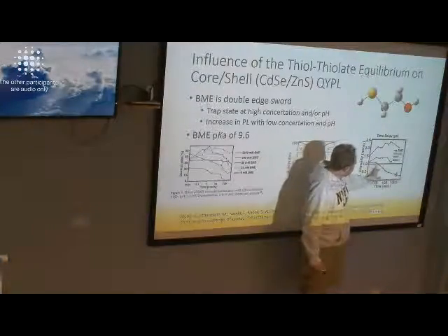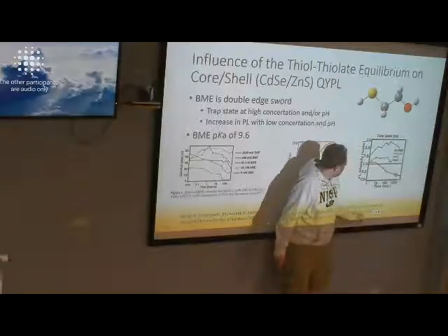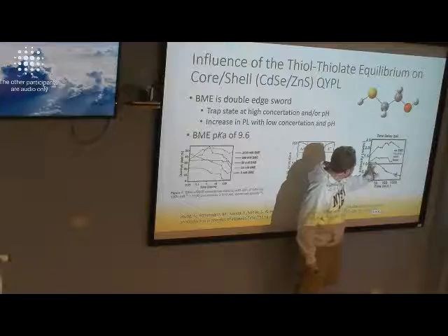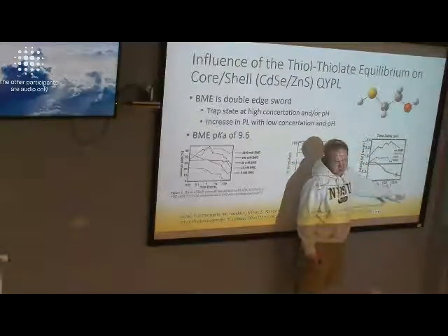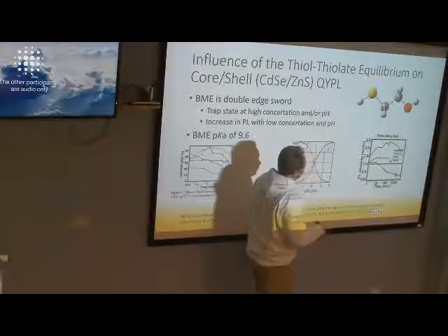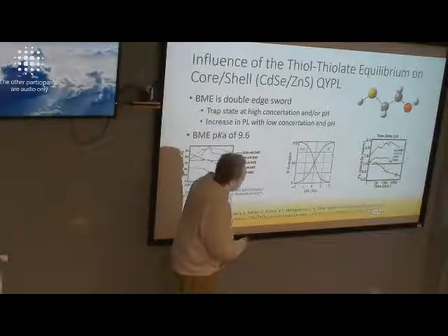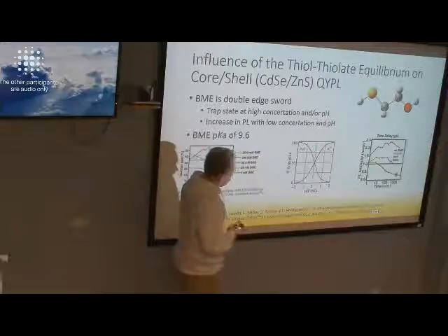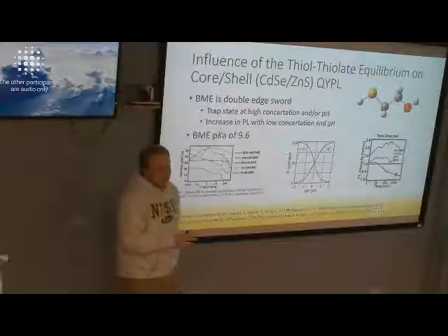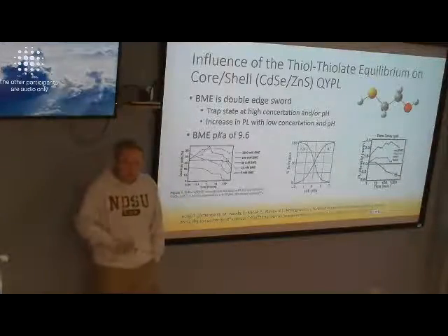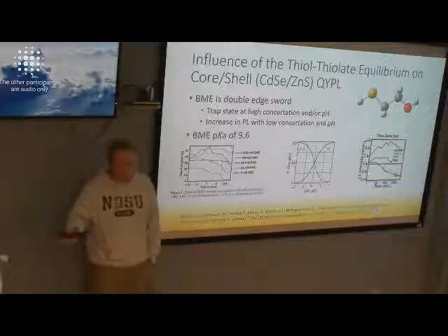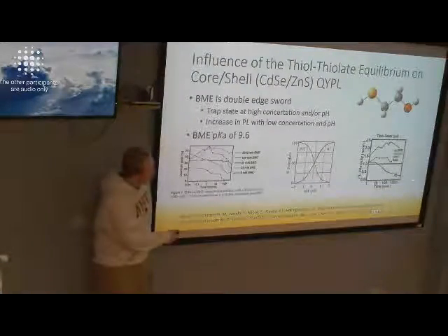And they saw that basic, over about a few hours, is trending to kill it, and then either neutral or acidic slightly goes up, and it has a higher magnitude for the acid form. And in their paper they said we can't really draw a whole bunch of conclusions from this because the results aren't dramatically different, as they are for the basic.